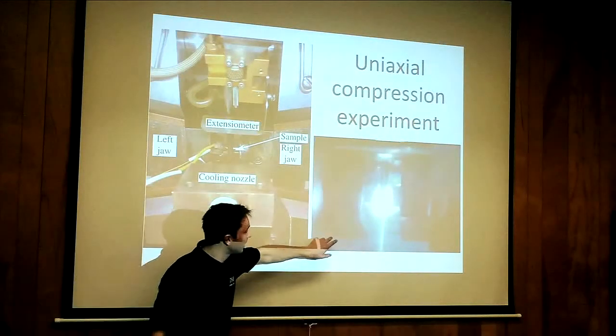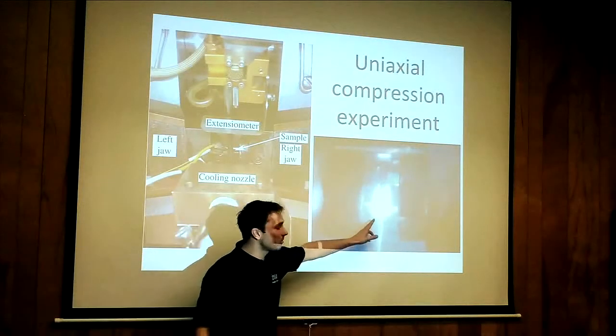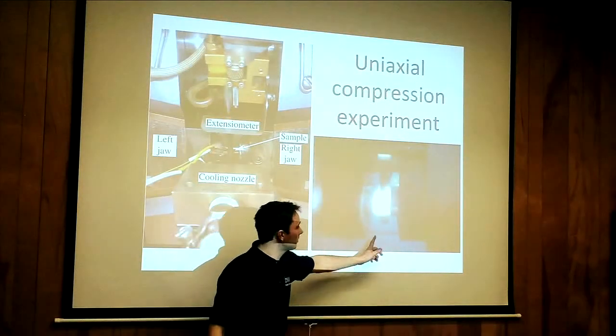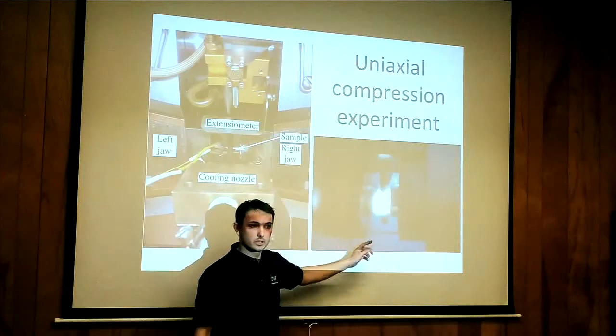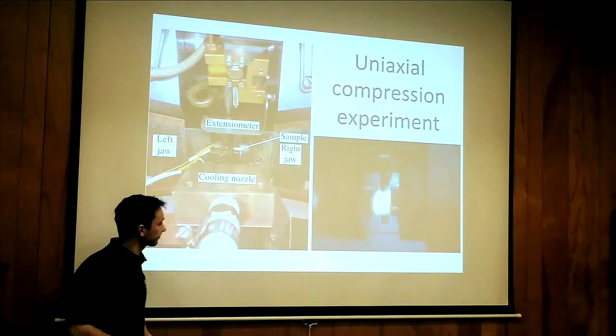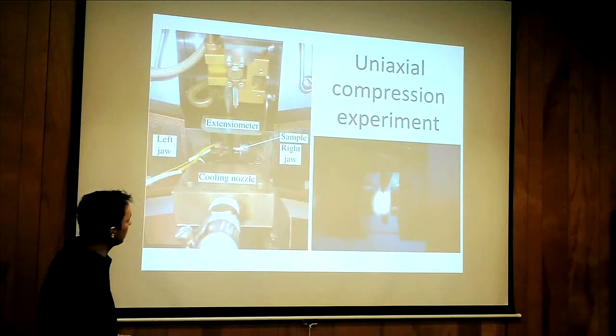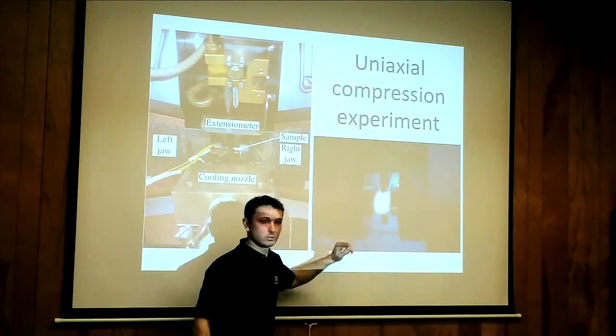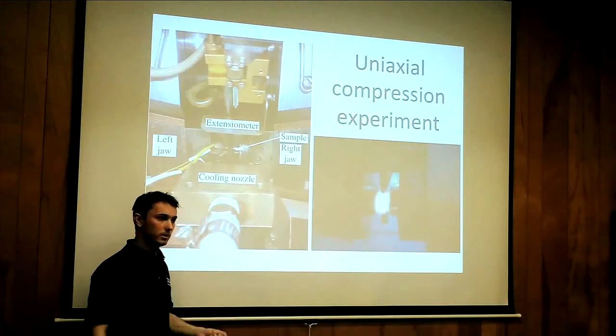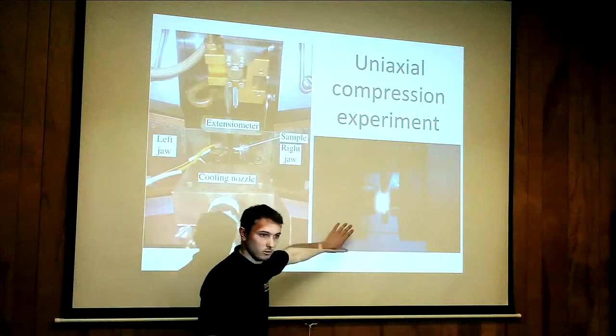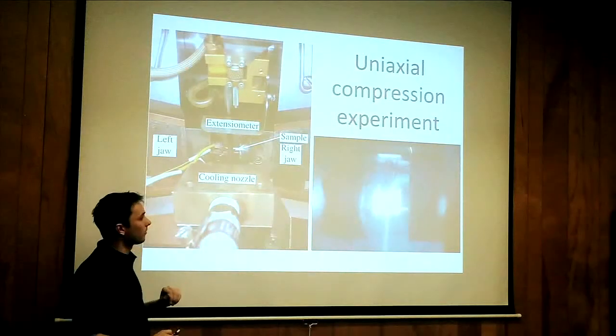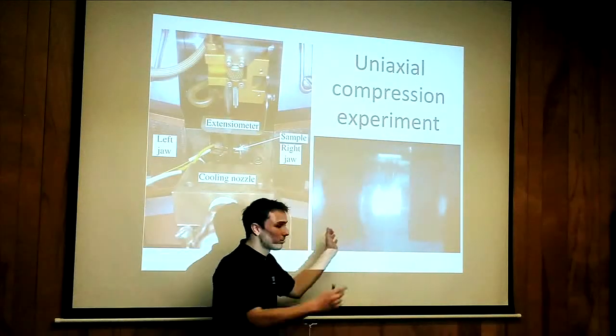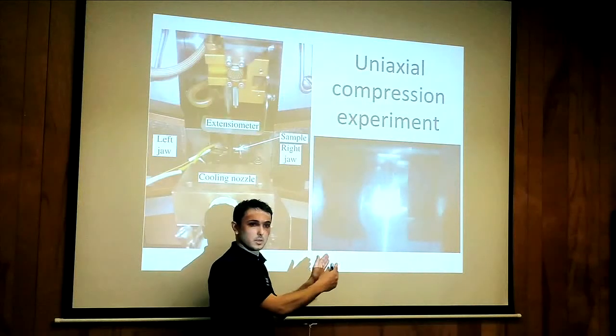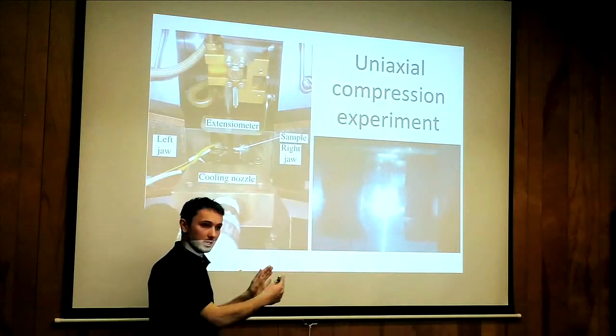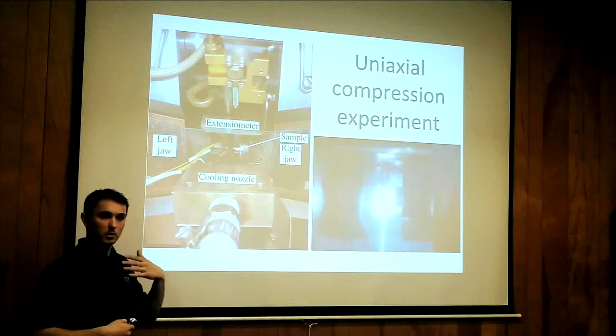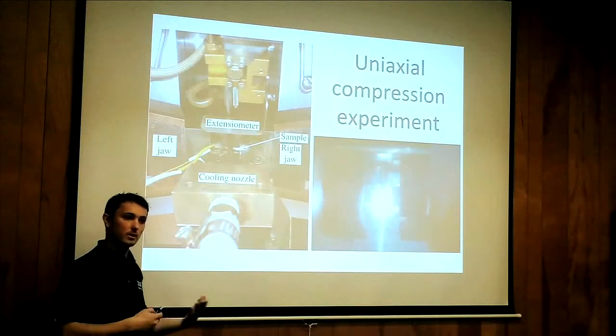And what you see here, it's a video where we have the sample being deformed and the laser shot firing 50 times per second on the sample. And so what I'd like to show you now is how those two parameters, the velocity and the attenuation, are varying during these things. So what we have to see is that depending on the rapidity at which you deform this material, the speed or the strain rate, the phenomena occurring in the microstructure will vary.